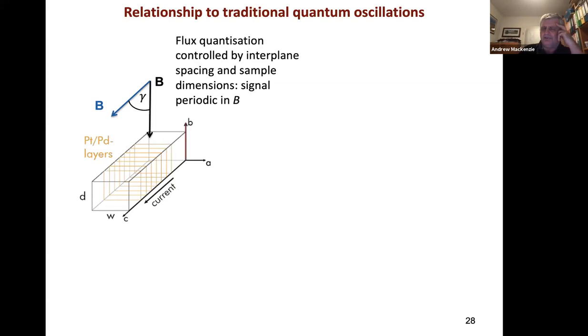And that leads to you getting an oscillatory signal, which is periodic in field. By the time you rotate the field out of the plane along the C-axis, there will come a point when the field is big enough that the cyclotron radius of motion of the in-plane electrons, just like for any quantum oscillation measurement, begins to be enclosed in the cross-section of the device.